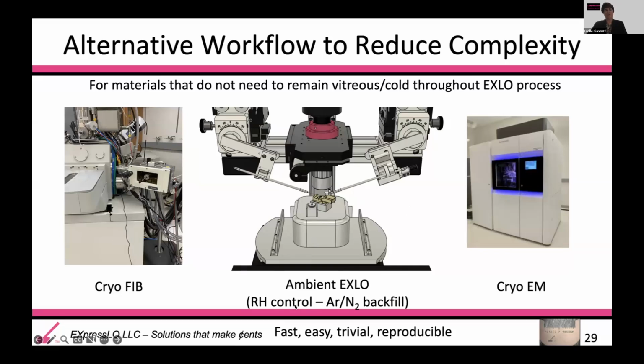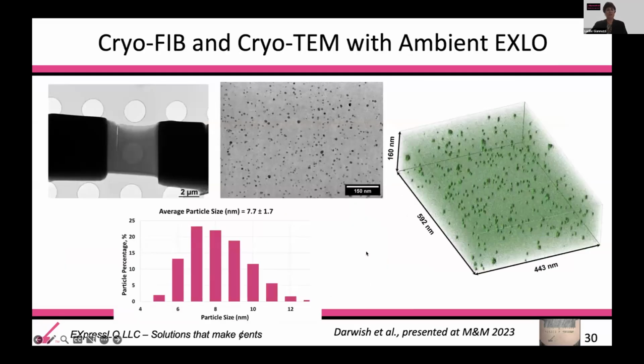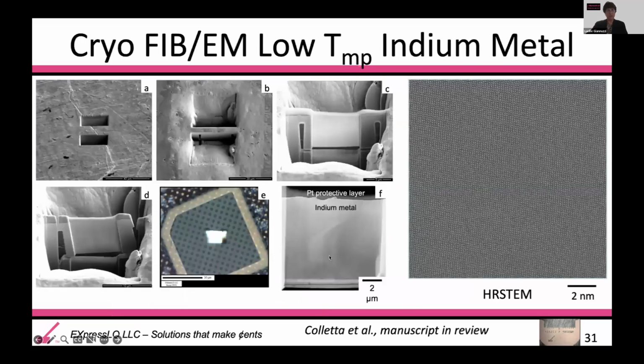can be done with humidity controlled and backfilled. So if you have beam sensitive materials, air sensitive materials, or materials that have to be FIB milled cold, such as polymers or other samples, this can be done quite easily. So here's some particles embedded in a polymer, and we were able to do some tomography here and do some particle analysis.